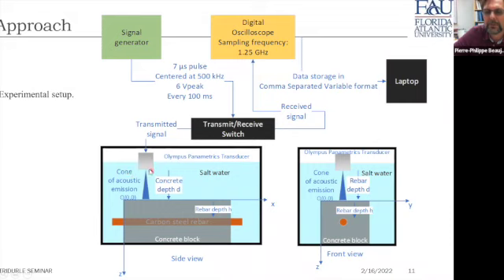Now, the cone of acoustic emission is originally starting from a set location along X. It is right over the rebar, as you can see from the front view to the right. The distance between the face of the transducer and the top of the concrete block is D. The depth of the rebar is H. And what happens is that we actually move the transducer along the X-axis while keeping the position along the Y-axis, which is shown over here, constant. So we pretty much line up the displacement or the position of the transducer with the position of the rebar.